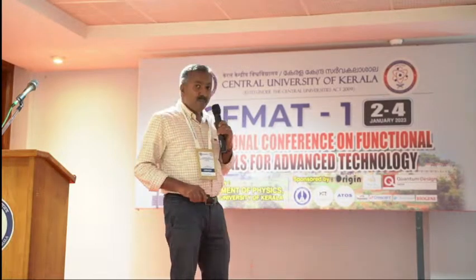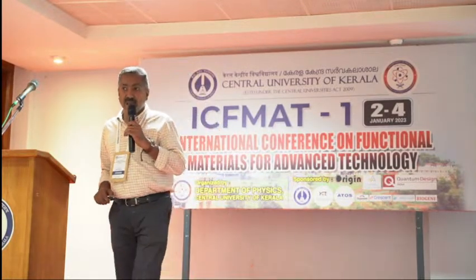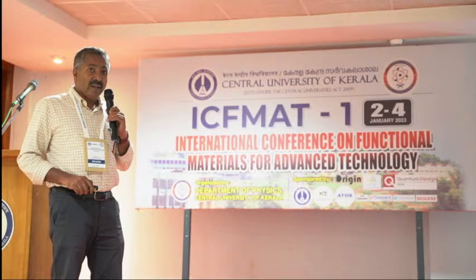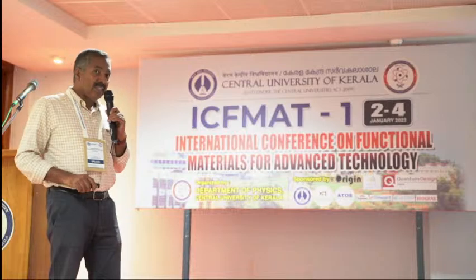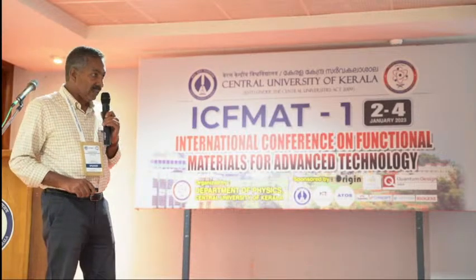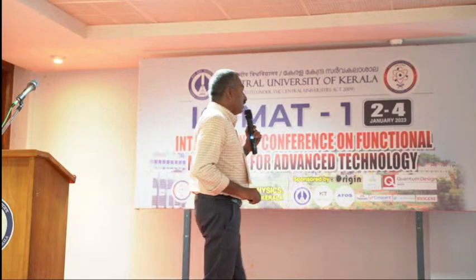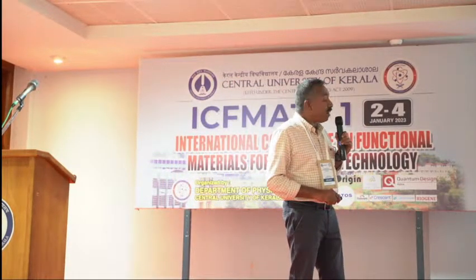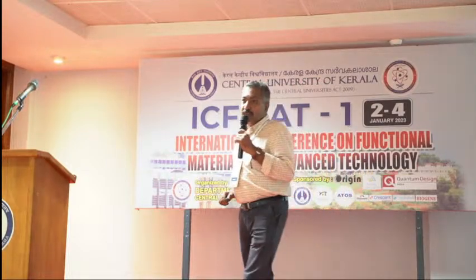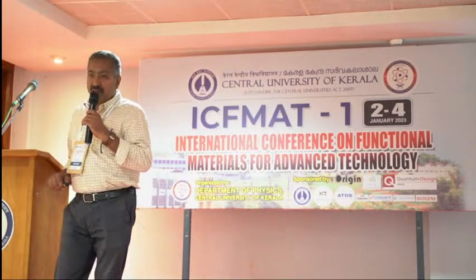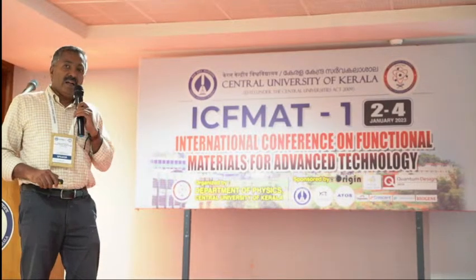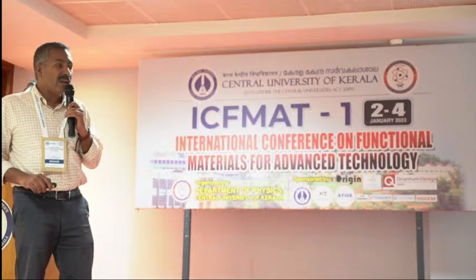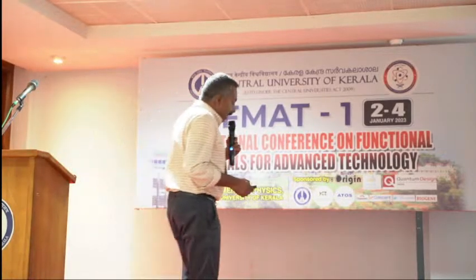And to the best of our belief, this is the first paper where, in a Z-scan experiment, we found that the Z-scan shown here is not exactly like what was shown in the original Z-scan paper by Sheik-Bahae in 1990. Here we could see humps which flank the valley, and we explained this in terms of the plasmon band bleach in the metal nanoparticles, which turned out to be correct eventually.